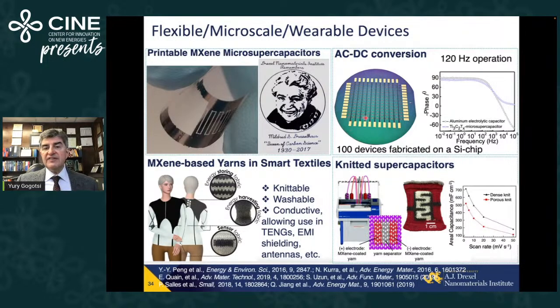For example, I have printed or fabricated interdigitated devices here, actually more than 100 devices on a silicon wafer, for very high rate operation, like AC to DC conversion at 120 Hertz, competing with, say, electrolytic capacitors, but having much smaller size and larger capacitance. We can make flexible devices.